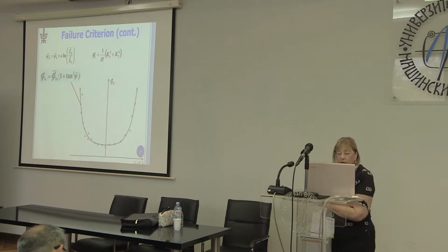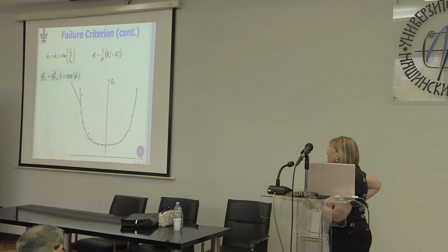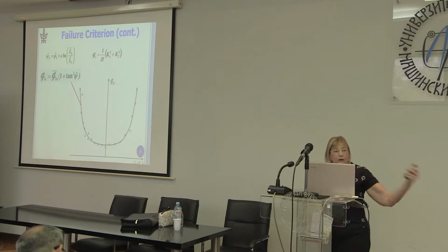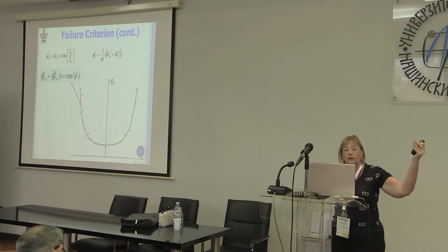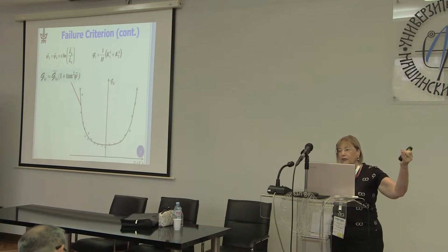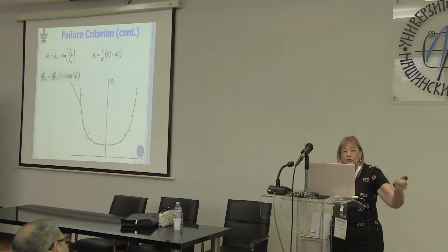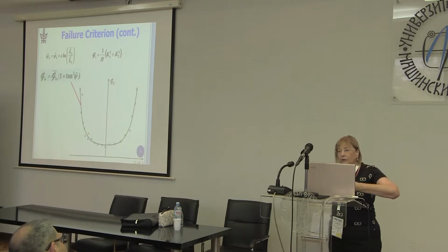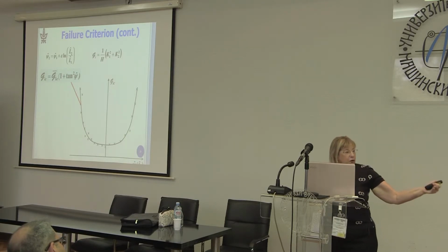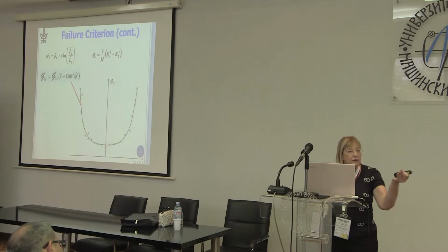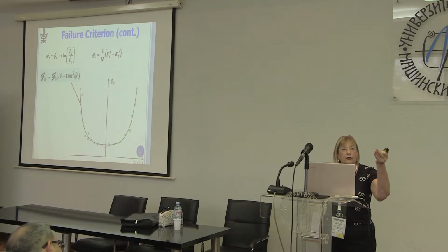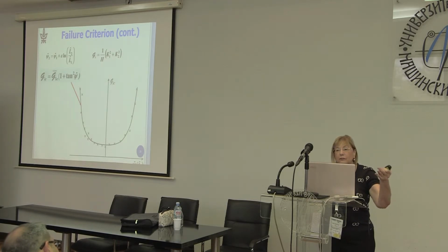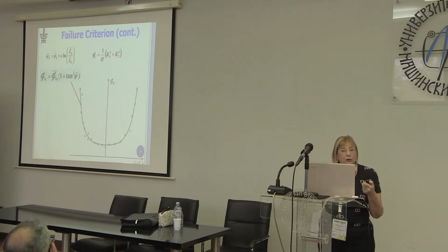And what does this curve mean to us? This is the failure curve. How do we use this failure curve once we've lined up the data? Let's say the interface in our structure is glass and epoxy, and we use the same conditions to make the interface in our specimen as the interface in our structure. And we measure the crack length, and we know the highest load that this structure is going to endure.